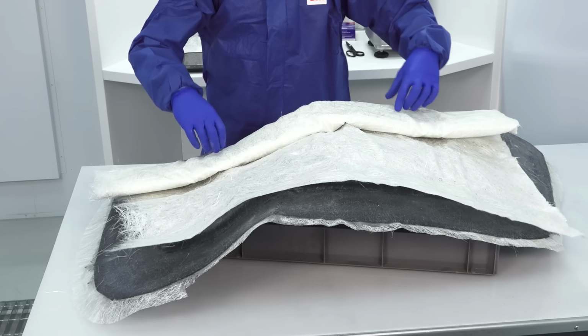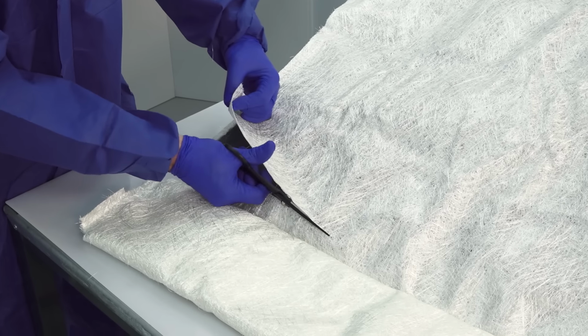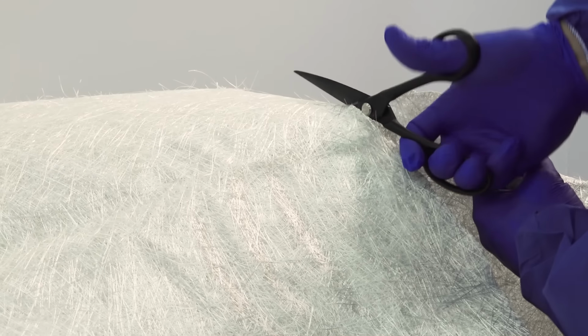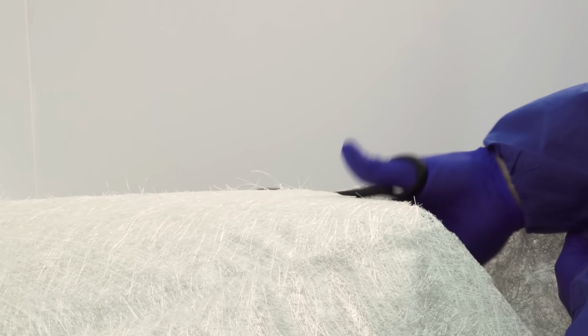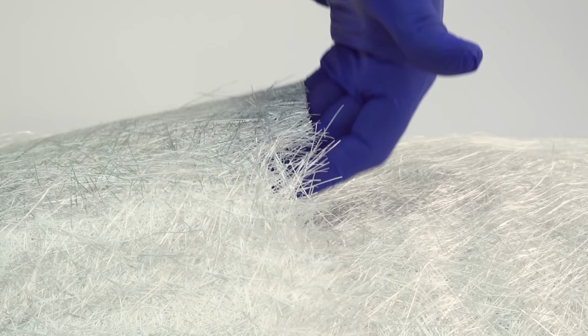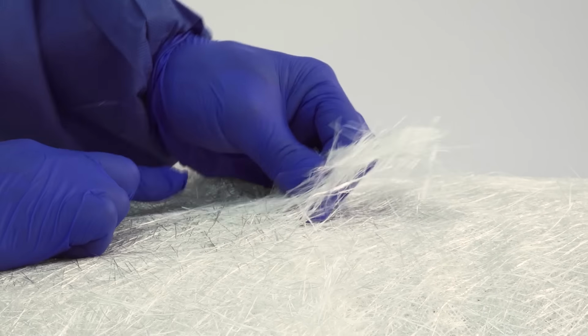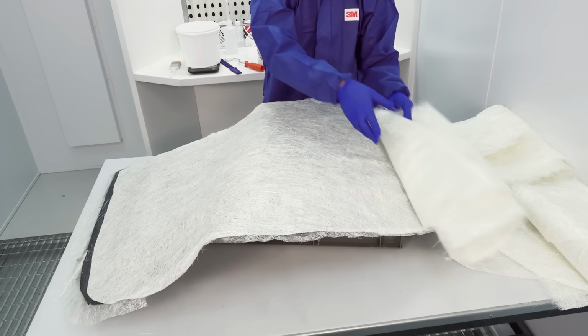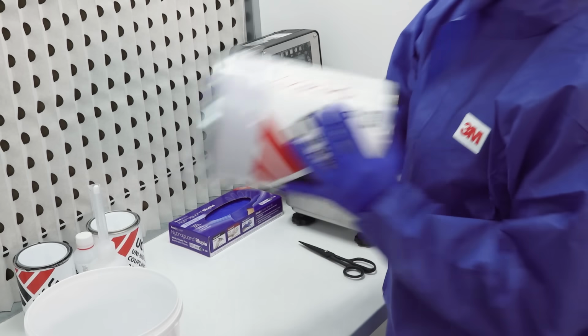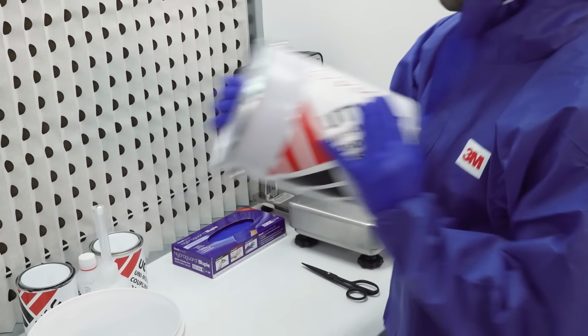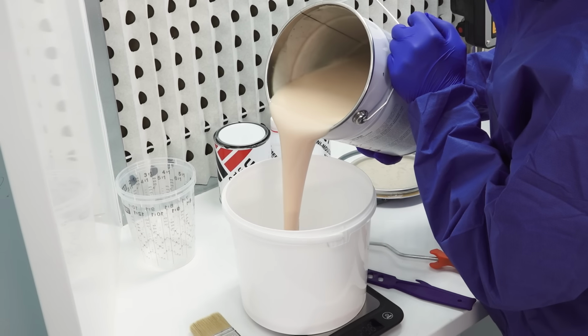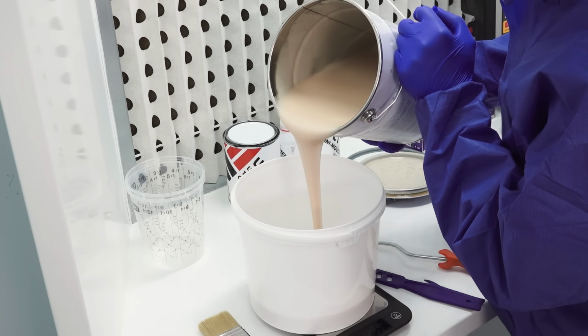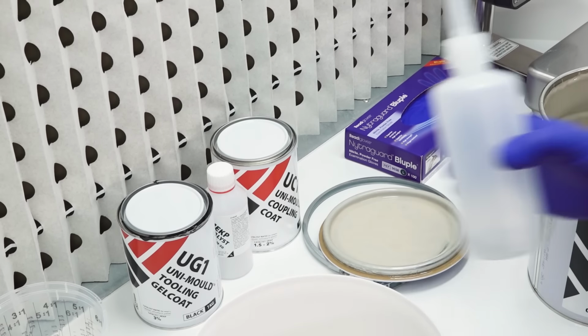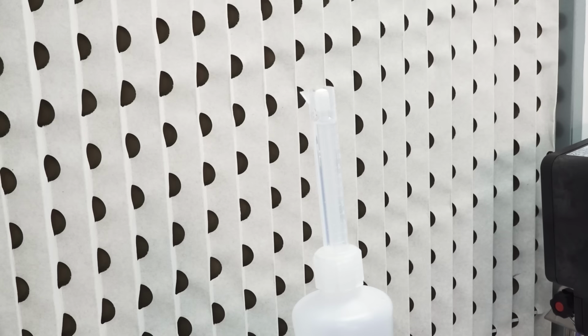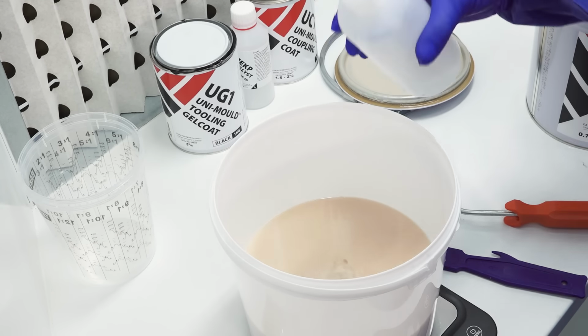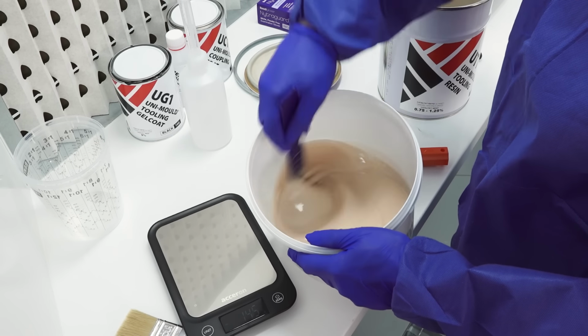The main reinforcement can now be prepared. This comprises 4 plies of a heavier 450 GSM chop strand matting. Tailor this to size in just the same way as you did for the first plies. Again, tearing the edges of your reinforcement will allow for a better join. The UG1 tooling resin should then be thoroughly shaken up or mixed to disperse the fillers which settle to the bottom when stored. You will need approximately 7 kilograms of the UG1 per square metre of mould, which is then mixed with 0.75 to 1.25% of MEKP catalyst. I typically use 1% unless working at the far ends of the working temperature range.